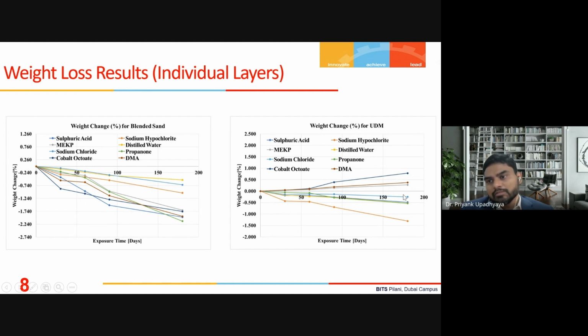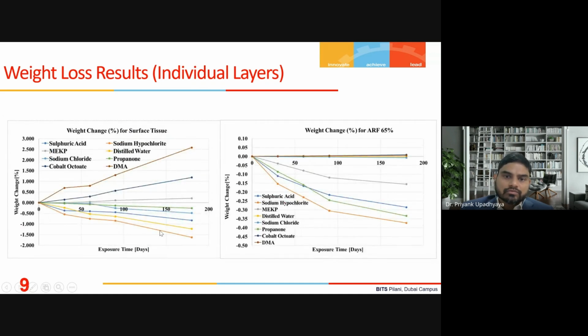This one is unidirectional mat. In this case, similar to the CSM, we notice that the weight is increasing for MEKP, DMA, and cobalt octoate, but for all other samples, the weight reduction is in the range of about 1% at 180 days. The last one we have is the surface tissue and the ARF layer. Surface tissue is a single layer of glass fiber that we are using there. A similar pattern is noticed here, but with slightly higher weight reduction of about 1.5%.